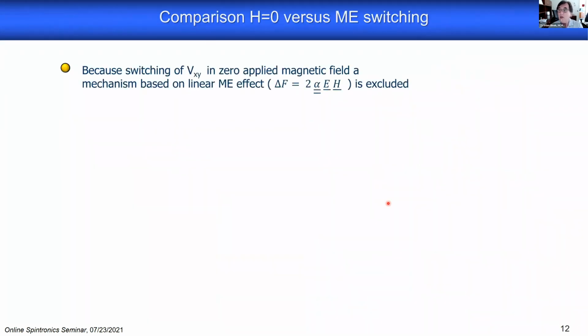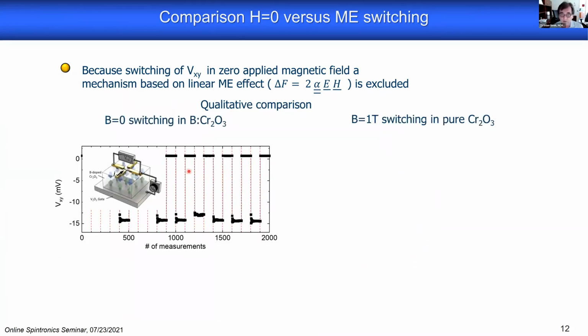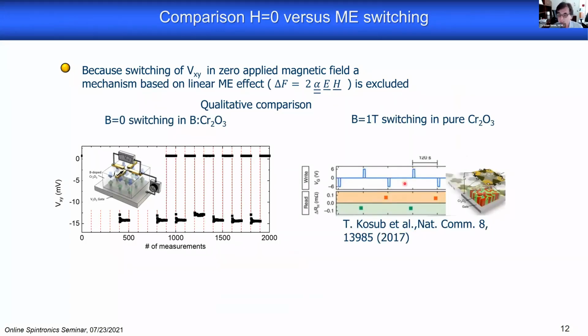Okay, so let me compare this finding with what happens in pure chromia. So we have the results, for example, from the Dresden group in pure chromia, and we have our results in the boron doped system. This is what the guys in Dresden did. The same type of structure, a Hall bar of the similar type on top, and they measured the Hall signal in the presence of an applied magnetic field of 1 Tesla. They changed this gate voltage, and by doing so, they switched the Hall signal symmetrically between negative and positive values. Why? Well, because the antiferromagnetic order parameter switches from up to down, and so switches the sign of the boundary magnetization and the sign of the signal. So that is a clear indication of 180-degree switching of the order parameter.